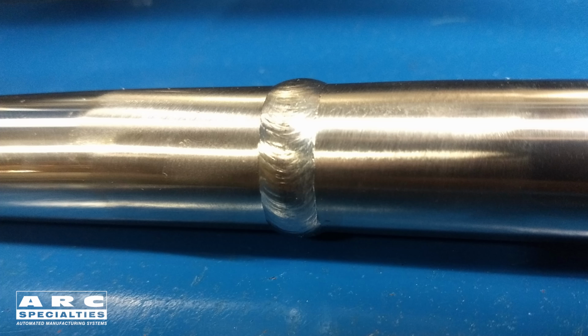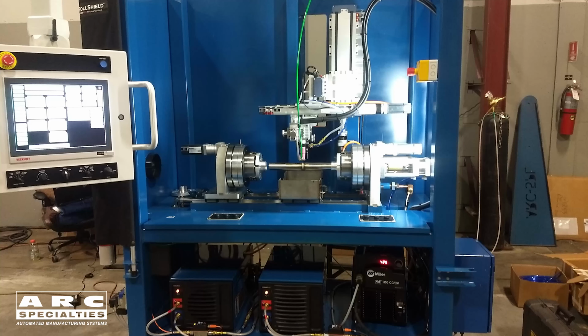When you're welding these nitrogen strengthened steels, you have to maintain a very low heat input. Otherwise, you'll lose the nitrogen from the part, and nitrogen is a critical austenite stabilizer in these alloys. So what we'll do here, in addition to minimizing heat input, is we'll water quench between passes and then air knife dry. And from the video, you'll observe that we're using cold wire rather than hot wire.